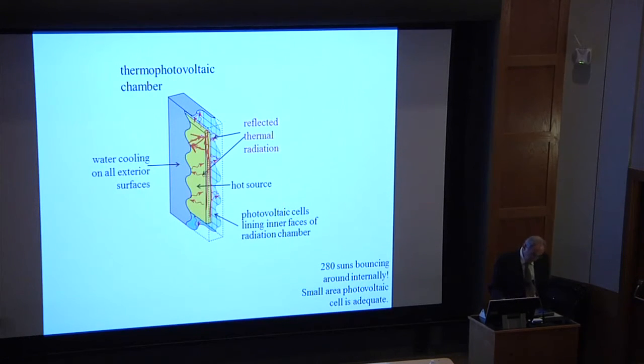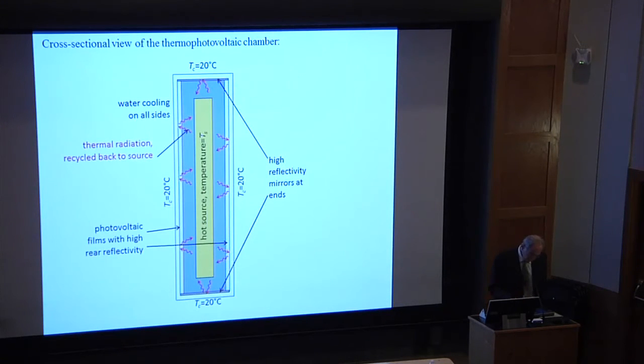Now, to understand what's going on, at 1200 degrees centigrade, the black body radiation is 28 watts per square centimeter, which is equivalent to 280 suns. So there's a lot of thermal radiation bouncing around. So it's a regime which we're not that familiar with, but one of the great truths is there's a lot of suns, and so the usual bugaboo in photovoltaics, which is the cost per unit area, you don't need a big area, because we're talking about 280 suns. You need an area more like a concentrator cell, and not like a flat panel cell, because there's all this thermal radiation bouncing around.